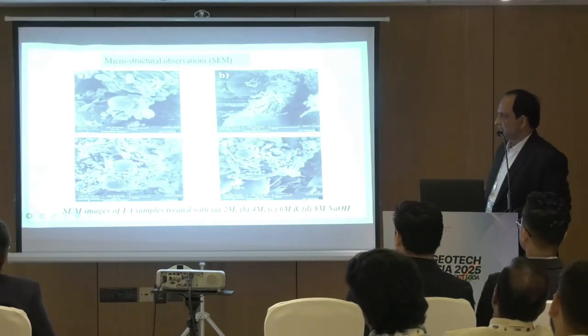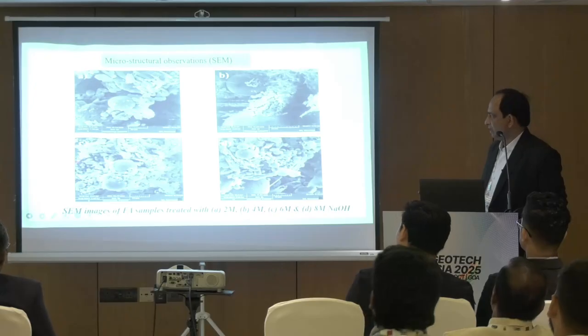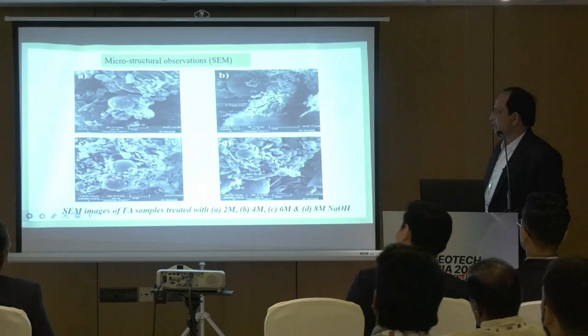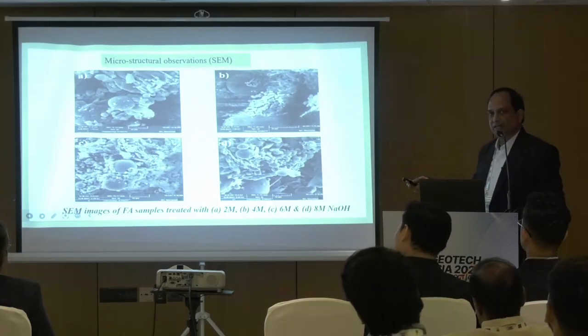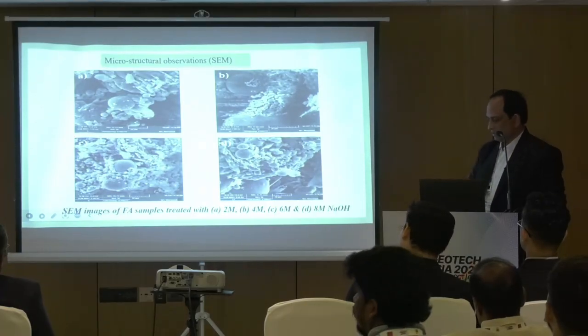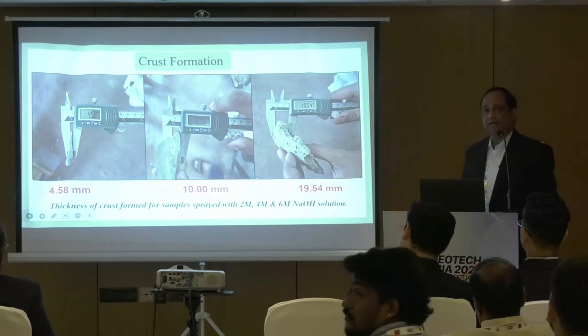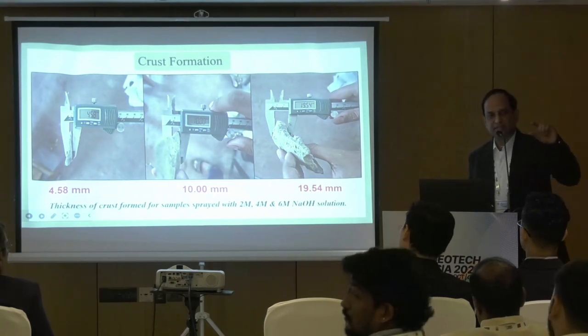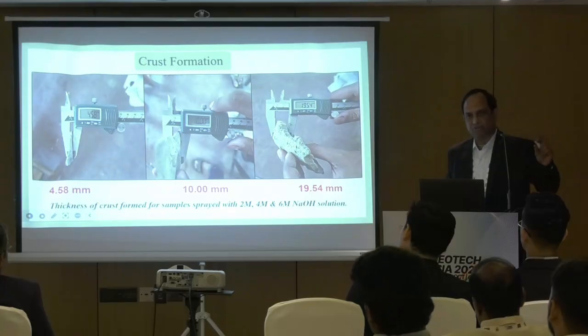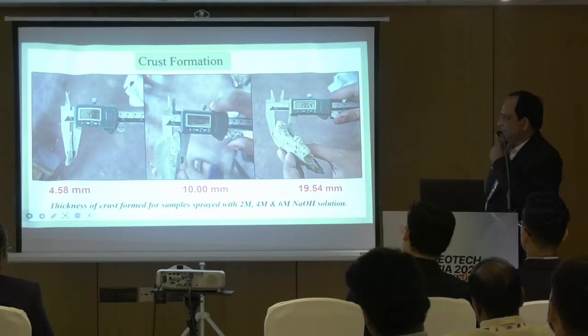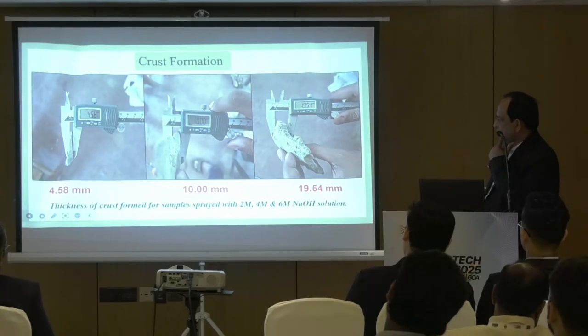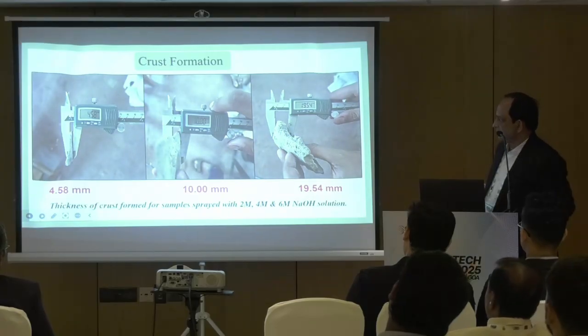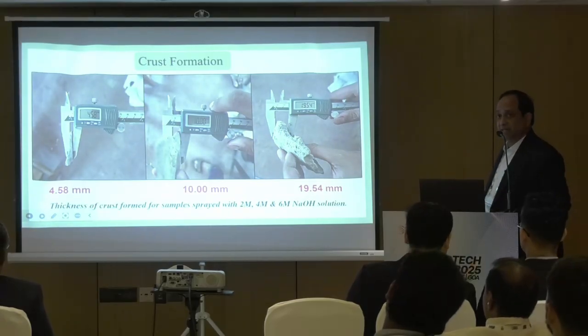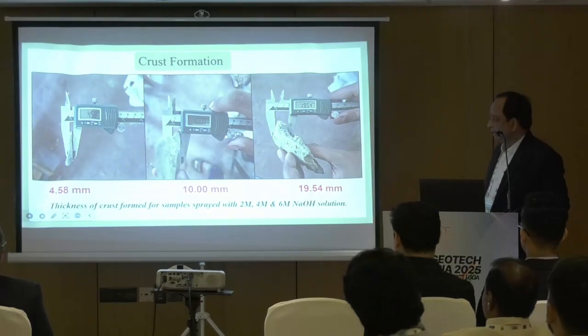Of course, even in SEM, there is a good amount of gel formation for 6 molar based on our findings. Therefore, we have selected 6 molar even for sodium silicate addition also. And we have calculated the thickness of crust, how much layer it is getting formed. With different molarities of NaOH, you can see here 4.58 and it is 19.54, almost 4 times increase with molarity. And it's a very good thickness.